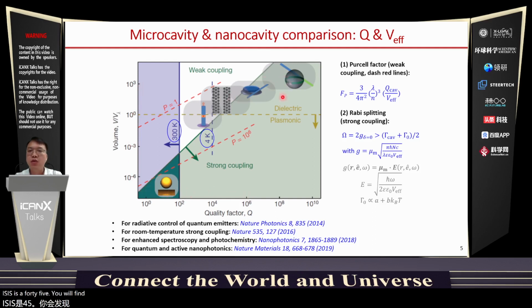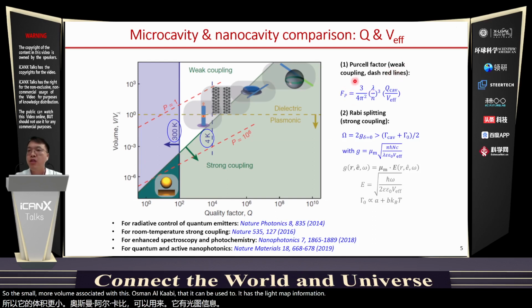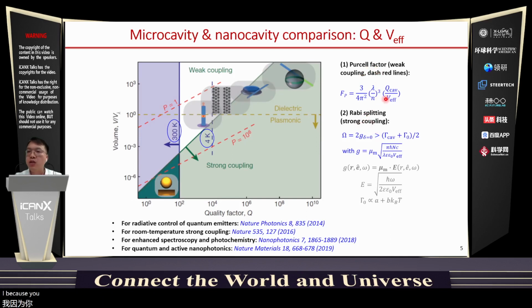You will find that those dielectric microcavities usually have much larger quality factors than the metallic nanocavities. But their problem is that the mode volume is also up to 10 orders of magnitude larger than the plasmonic nanocavities. So the small mode volume associated with these plasmonic nanocavities can be used to enhance the light-matter interaction in both the weak coupling regime through the so-called Purcell effect, or in the strong coupling regime. As you can see from these equations, as long as you have a very small mode volume, you can always have a very large Purcell factor or quite large coupling strength in your system.